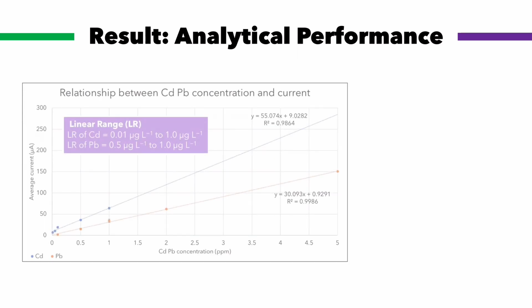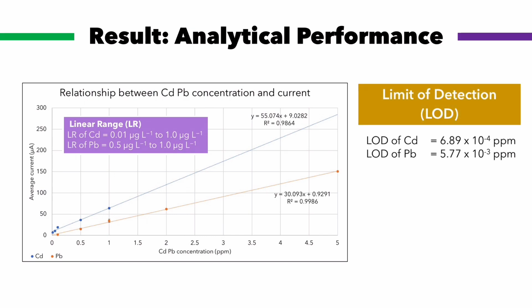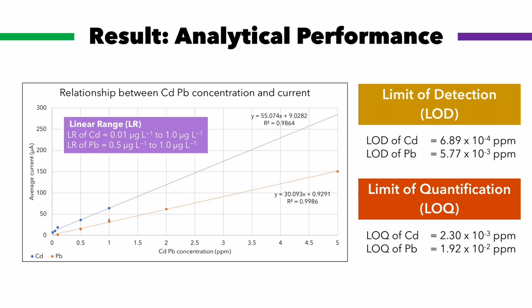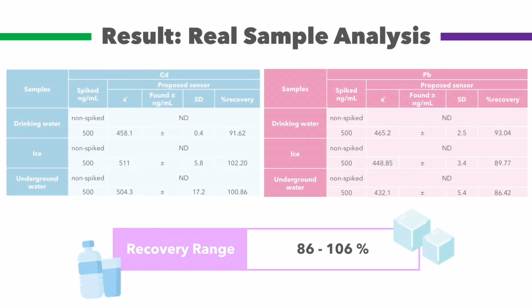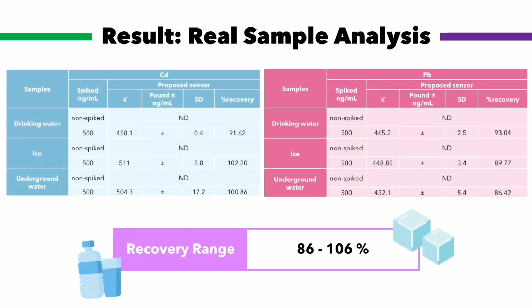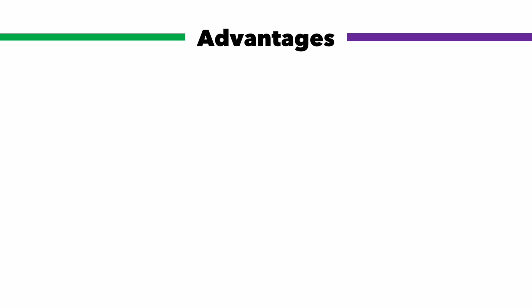The relationship between the concentration and the current was linear, with the range from 0.01 to 1.0 microgram per liter of cadmium and 0.5 to 1 microgram per liter of lead. Not only that, but also the value of limit of detection and value of limit of quantitation were calculated and resulted in the acceptable range. The proposed sensor was applied for the determination in various water samples with acceptable recoveries in the range of 86 to 106%. Overall, the paper-based sensor exhibits significant advantages over the previously used methods in these following aspects.